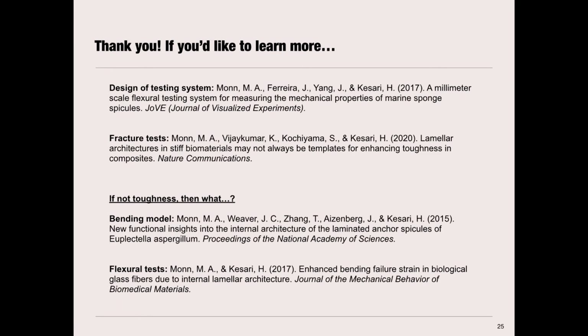It's constrained in how it can nucleate daughter cracks, and this nucleation of daughter cracks, as a mechanism for redistributing stress, is the primary way that toughness is enhanced through this Cook-Gordon-like mechanism, with cracks nucleating at weak points ahead of the crack tip. And so that's less able to happen if you don't provide a very large surface for which it could happen. If you flip the curvature and looked at a concave curved interface instead of a convex one, it could actually promote that type of mechanism and potentially enhance toughness, but we didn't really investigate that.